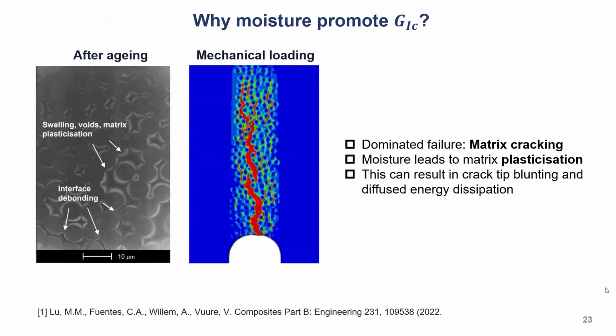This does help us understand why moisture can promote the mode 1 fracture toughness. Because from that simulation, we can see most of the failure happening in the matrix. The dominant failure is the matrix cracking with some amount of interface debonding. Because the moisture can lead to matrix plasticization, this can introduce crack tip blunting and contribute to more energy dissipation. That's why it can promote the mode 1 fracture toughness.